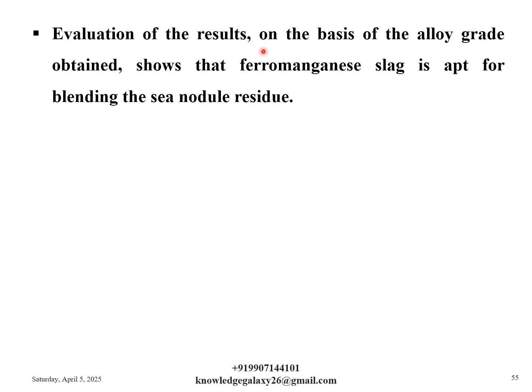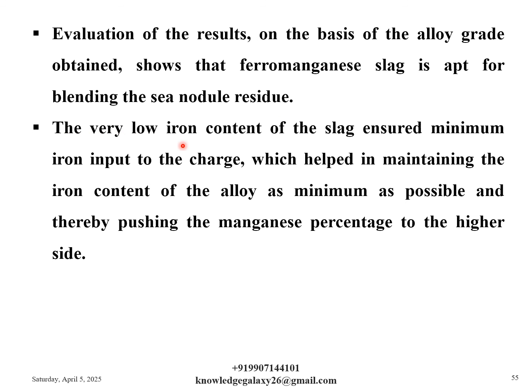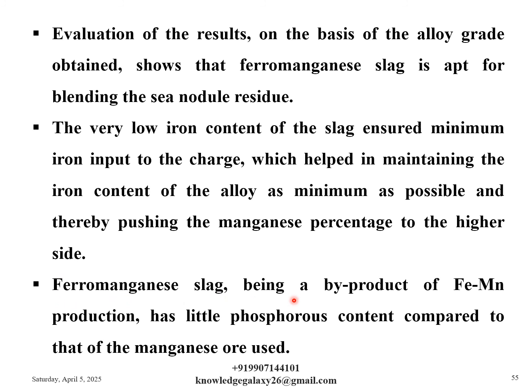Evaluation of the results on the basis of the alloy grade obtained shows that ferromanganese slag is apt for blending the sea nodule residue. The very low iron content of the slag ensured minimum iron input to the charge, which helped in maintaining the iron content of the alloy as minimum as possible and thereby pushing the manganese percentage to the higher side. Ferromanganese slag, being a byproduct of ferromanganese production, has little phosphorus content compared to that of the manganese ore used.